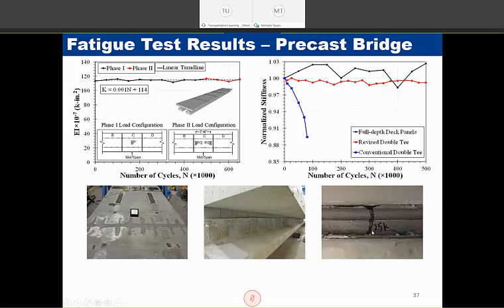Our conclusion was that because we used latex modified concrete for the open joints, and previous studies had mentioned that latex modified concrete has better durability. That's why we used it for the open joints. However, latex has a very fast setting time. In 30 minutes, it gets too hot, and it's 4,000 psi strong. This open pocket was the last one that we poured, so it was around 30 minutes. So our best guess was this was just a bad pour because it was the last one that was poured. Besides these minor damages, they can be well treated using a technique that is out there, or using a better grout, and should be taken care of.